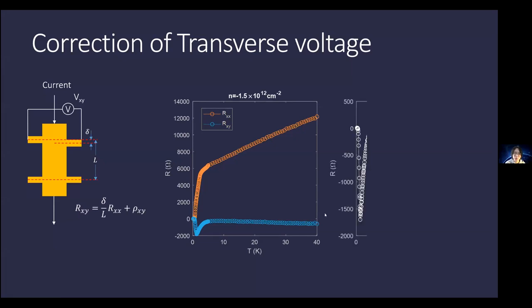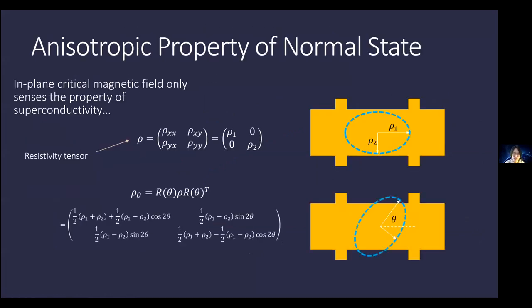Yeah, that's a very good question. So in terms of the normal state anisotropy, we don't have a way of really determining the angle, as you can see. We can only tell whether there is an anisotropy or not. But this we have repeatedly observed in many samples, in three samples in almost the same range. The superconducting anisotropy, on the other hand, we see basically in every sample.